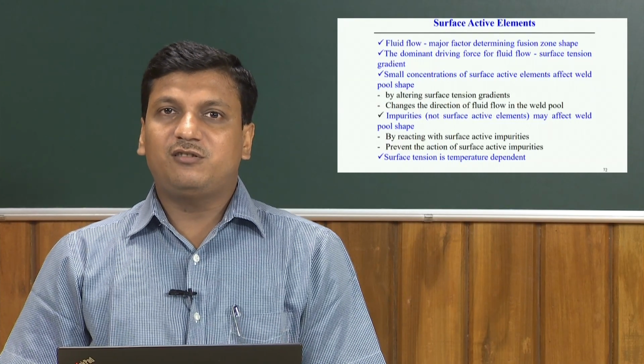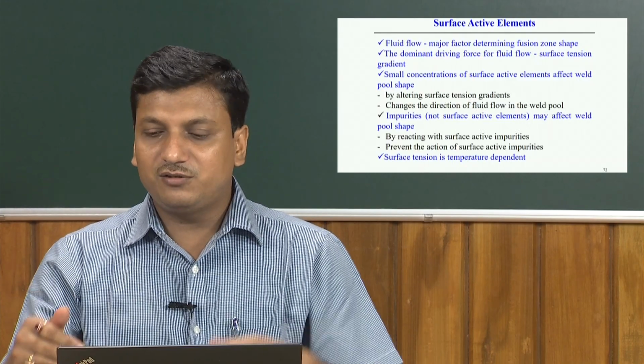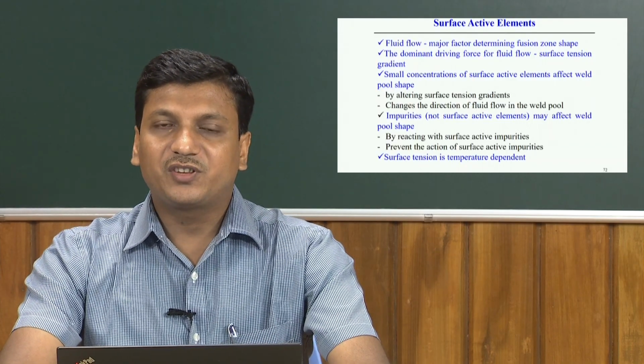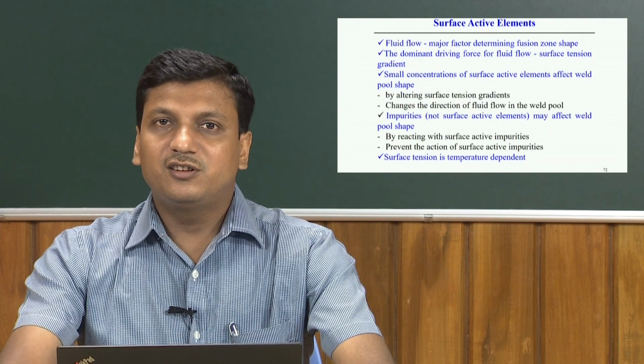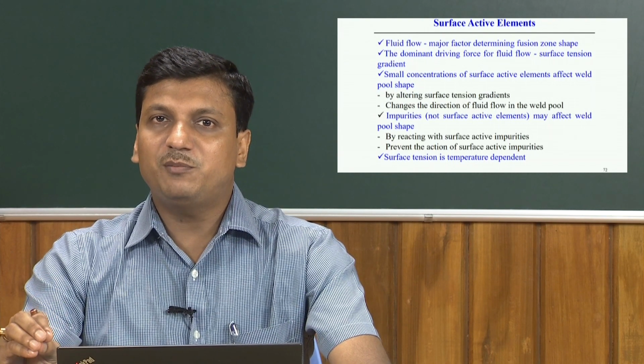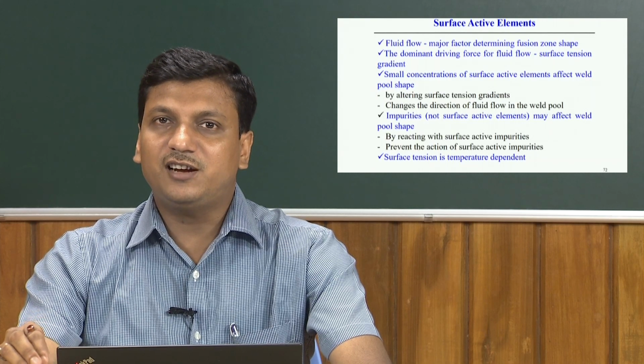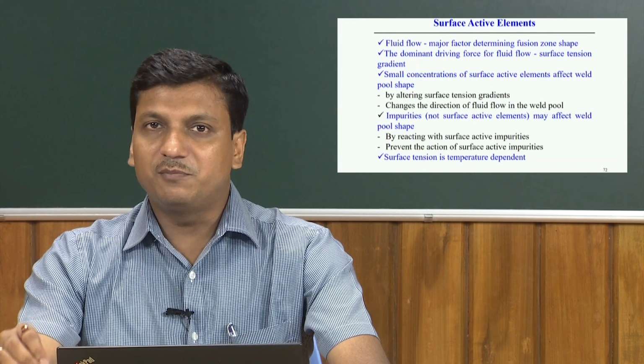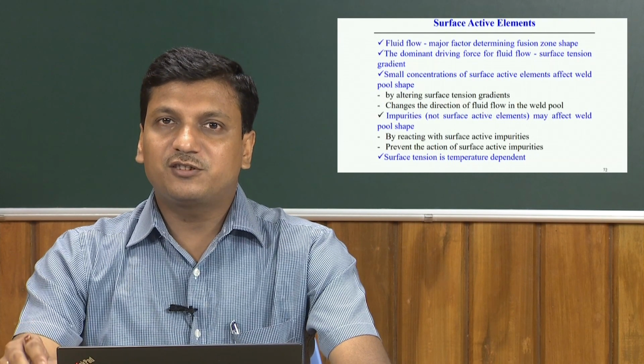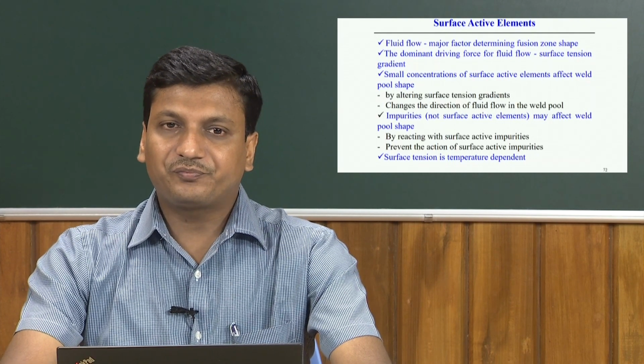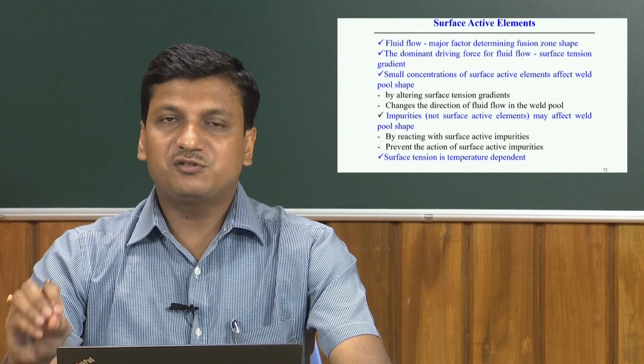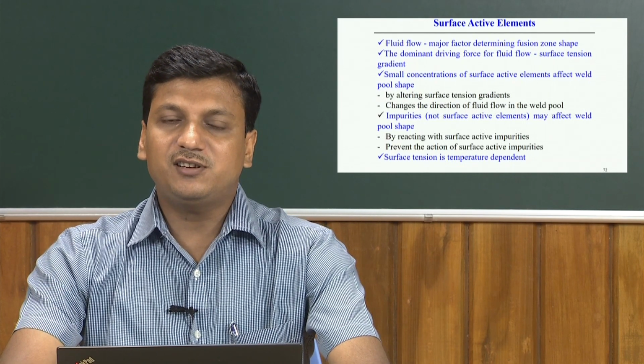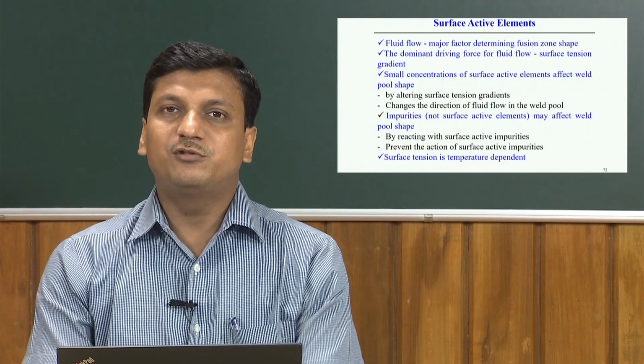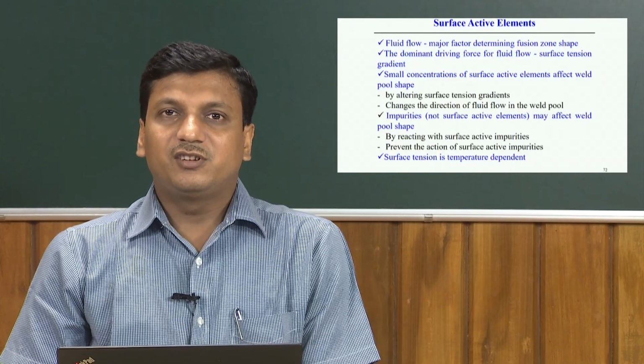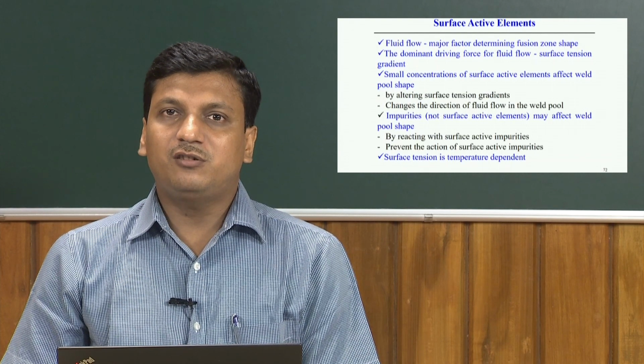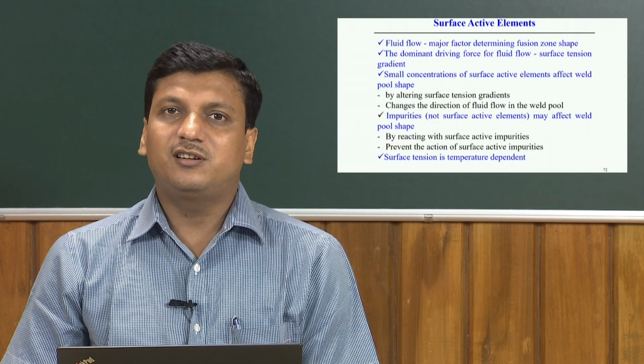So, definitely not only the surface tension force, rather it is better to say the surface tension gradient, because the surface tension gradient depends on the composition of the metal. Not only that, it also depends on the temperature. So, it is a function of the composition as well as temperature. Now, sometimes a small concentration of surface active elements actually affects the weld pool shape. For example, if we consider pure iron, and for example, if we consider steel,